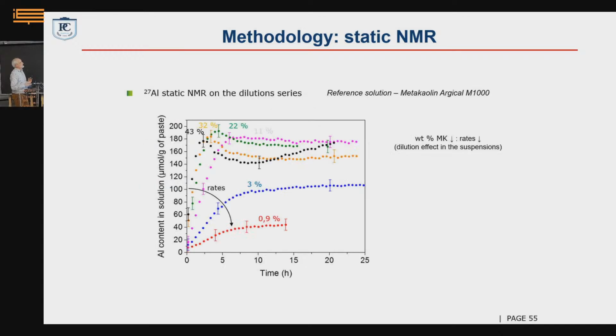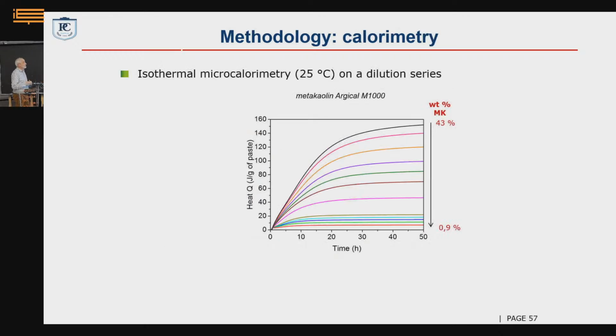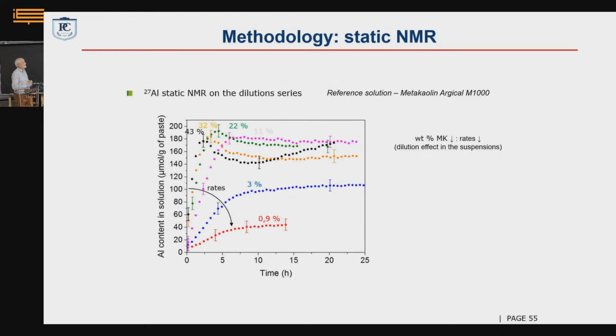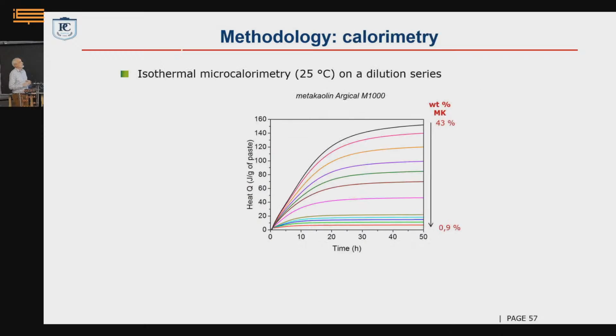Okay, so if we do that with different amounts of calcined clay, metakaolinite here, we have different curves. Obviously, the more metakaolinite we put, the more surface we have, so the more dissolution there is. But if we cross that with calorimetry, so we measure at the same time scale the heat released, varying the amount of calcined clay in the activating solution.